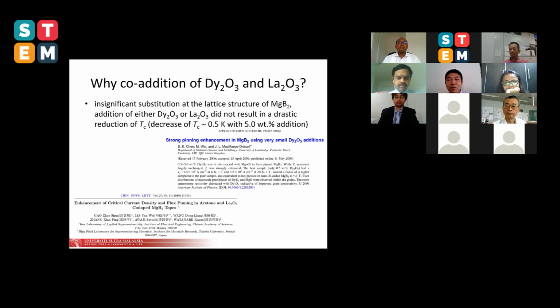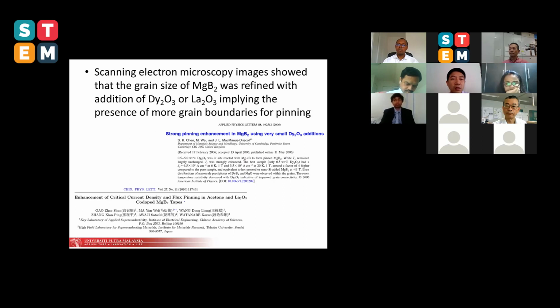Let's look at the motivation for this work. There are several reasons why we choose dysprosium oxide and also lanthanum oxide. First of all, we know that the two dopants do not substitute into the lattice structure of MgB2. If that is the case, then the dopant does not decrease the Tc. For example, for dysprosium oxide addition of about 5.0%, there's only a reduction of Tc by about 0.5 Kelvin. Same thing as reported for lanthanum oxide, the reduction of Tc is also very small, less than 1 Kelvin, with about 5-8% of addition.